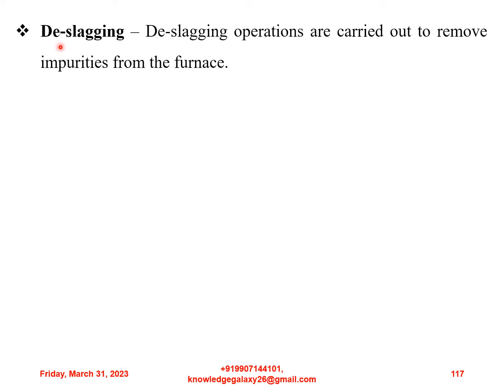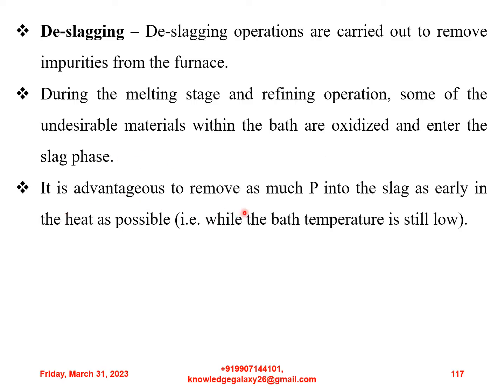Next phase is deslagging. Deslagging operations are carried out to remove impurities from the furnace. During the melting stage and refining operation, some of the undesirable materials within the bath are oxidized and enter the slag phase. It is advantageous to remove as much phosphorus into the slag as early in the heat as possible, that is, while the bath temperature is still very low. I hope you remember that I have already described this in detail in the previous slides.